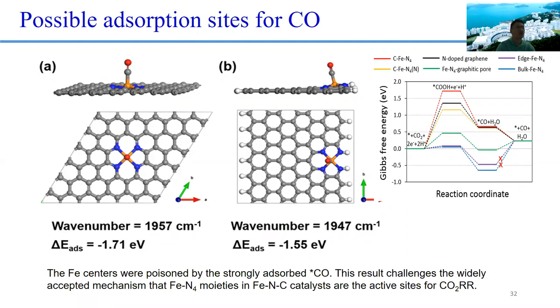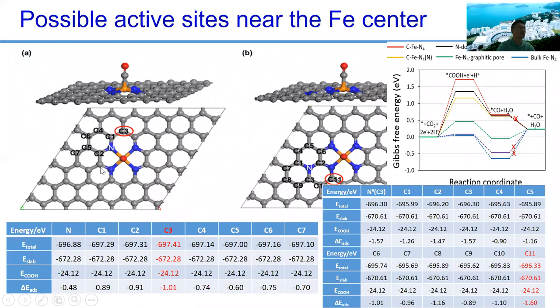And how about the atoms around this iron, for example, the carbon, for example, the nitrogen. We also did the calculation. But I found that even though the last step, removing the CO, is very, very easy, the first step, the adsorption of the CO2 and the corresponding COOH, is actually very, very weak. This is the red curve, and the black and yellow curves. So that means it's not feasible.